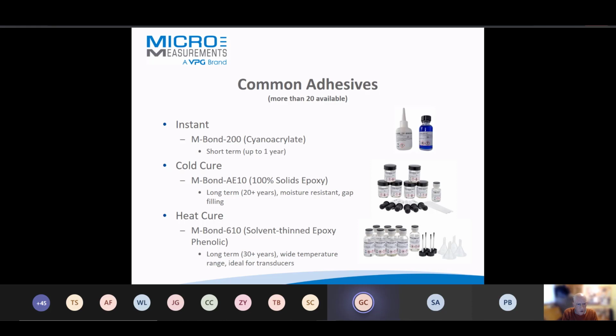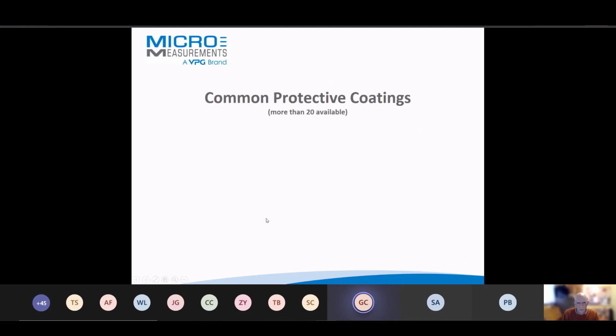And then if you want the ultimate performance, heat cure adhesives, something like M-Bond 610. Almost every commercial load cell you purchase will be using this adhesive to hold the gauges down. 30 plus years, in fact one of our divisions has now got an MTBF of 50 years using our strain gauge adhesive. So really good if you want the widest temperature range, the longest life, -269 to about +370, so very wide ranging temperature as well. Used a lot in superconducting magnet applications for that cryogenic capability.